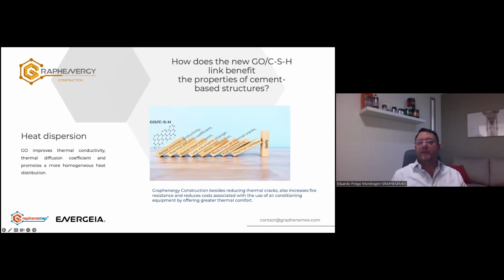GO increases the fire resistance of concrete. This means that the structure can withstand higher temperatures for a longer period without losing its integrity. This benefit is crucial for the safety of buildings, especially in fire situations. Thanks to the heat dispersion properties of GO, significant cost reductions can be experienced in air conditioning equipment usage. A structure with GO can maintain more stable and comfortable temperatures, leading to energy and air conditioning cost savings. In fact, a reduction of up to 3 Celsius degrees in indoor temperatures has been observed in constructions using GO additives, benefiting both the environment and the economy of property owners.